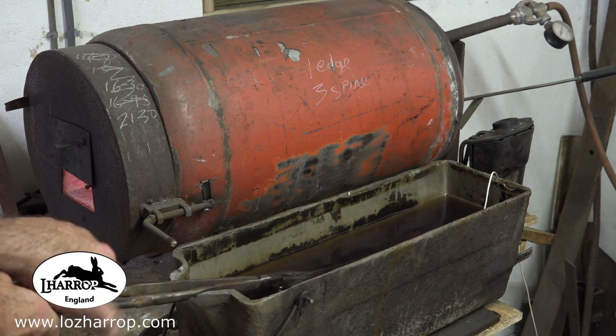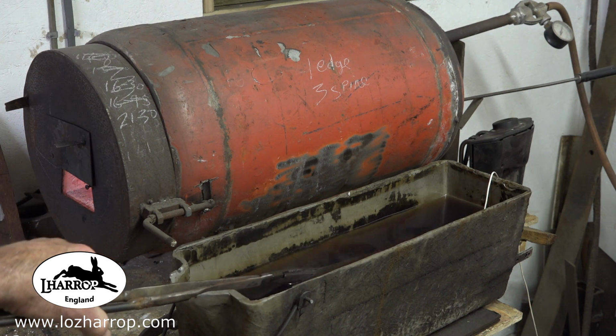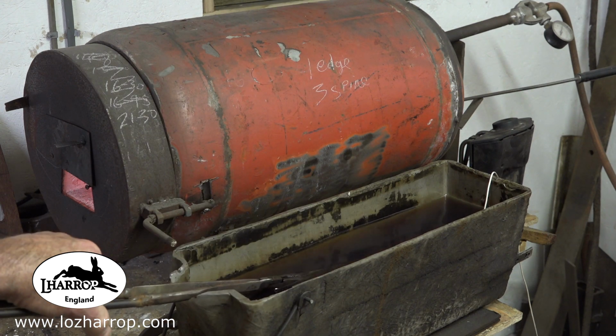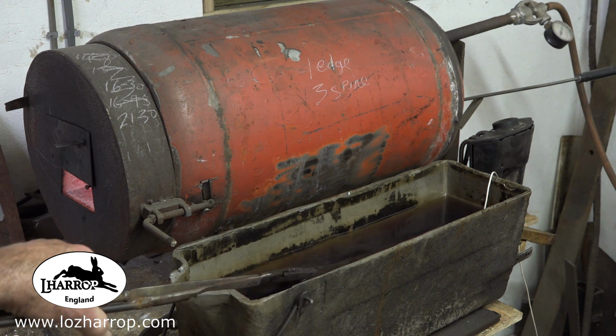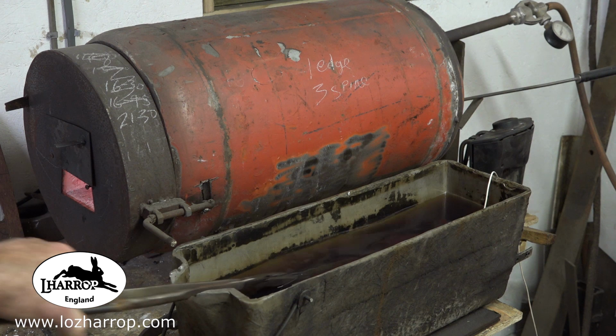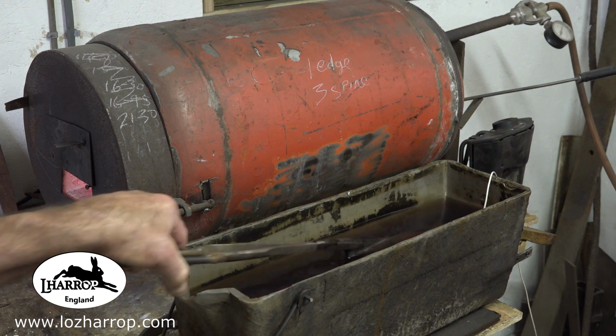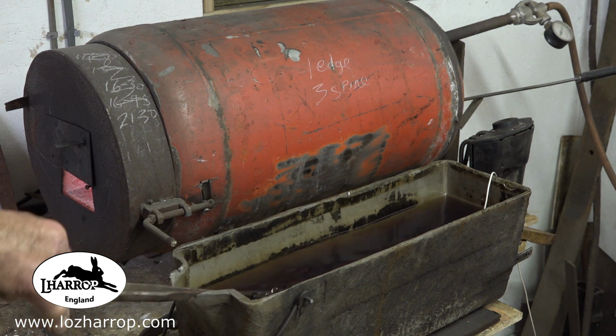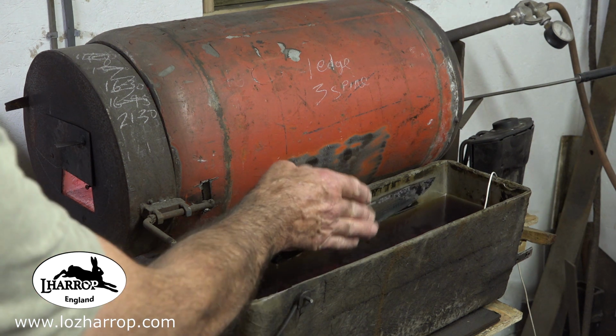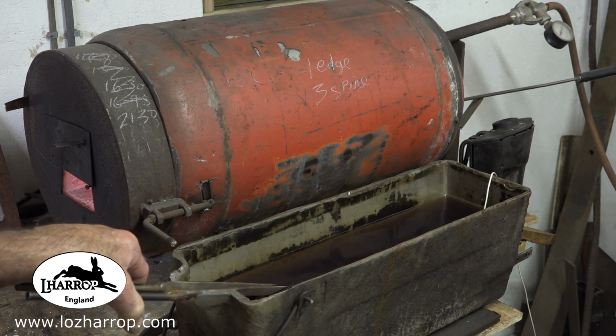Never move the knife from side to side, always up and down. You'll cause a bend if you start slashing it around sideways. So you can move it forwards, backwards, up and down. I always check the side of the blade with my finger, and when I can touch that, I know that the quench is done, or that it's been in the quench long enough, should I say.